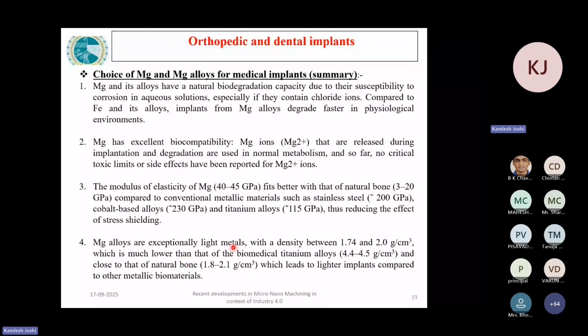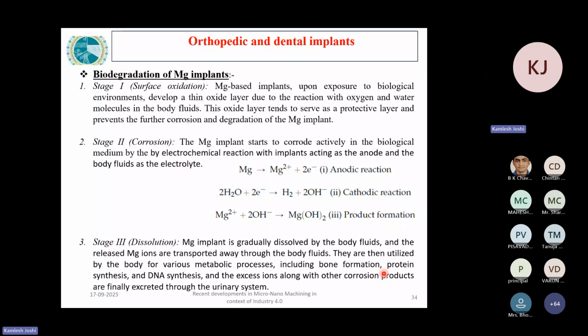They are also exceptionally light materials. The density lies around 1 to 2 grams per cubic centimeter, which is much lower than titanium alloys, which are around 3 to 4 times the density of magnesium alloy. And this density is closer to the natural bone, which leads to lighter implants compared to other metallic biomaterials. Here we have seen the three steps of biodegradation. First, surface oxidation happens. Magnesium implants, when they are exposed to the biological environment, develop a thin oxide layer as seen in the previous slide.